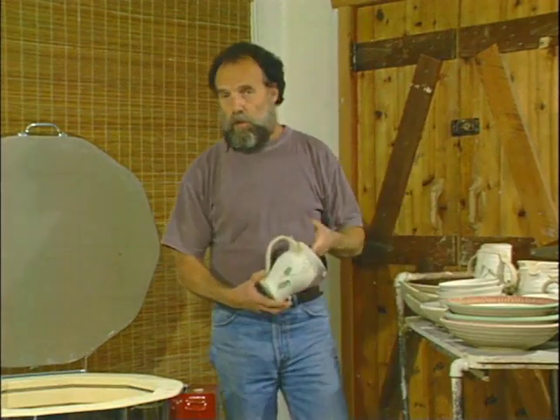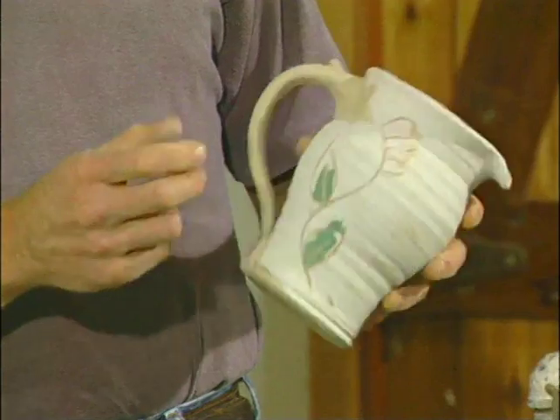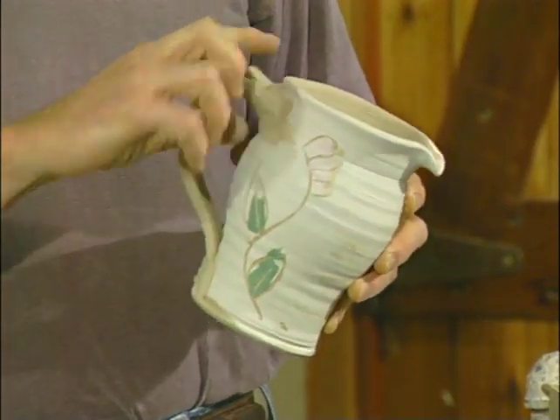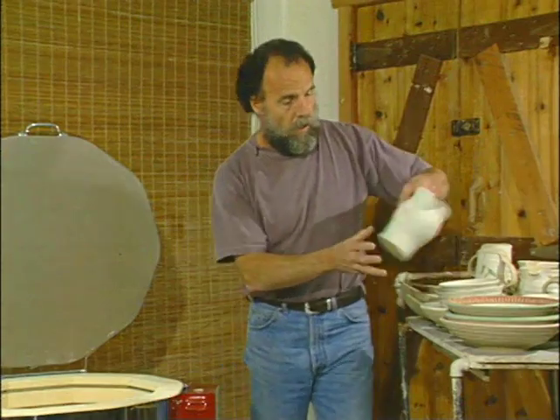Here we are with some pots that have been drying on the shelves of my studio now for several days, and they appear to be dry right through. It's important that the pots be dried right the way through, otherwise there's the likelihood of explosion due to water content when you're doing the bisque firing. Bisque firing is a firing to a lower temperature than we're going to use when we do the glaze firing.